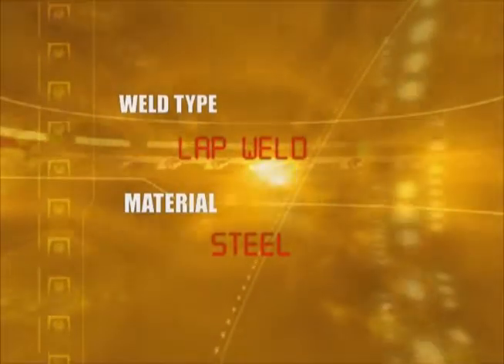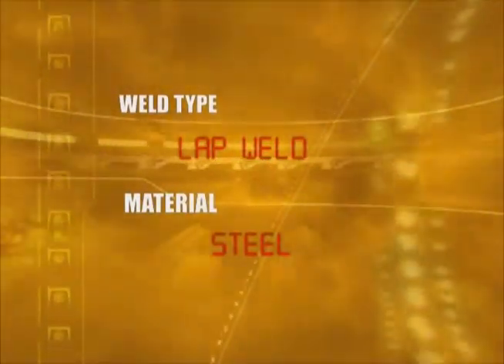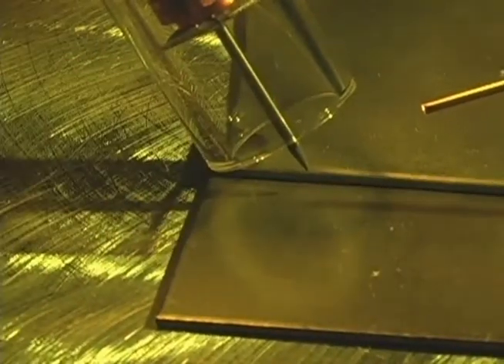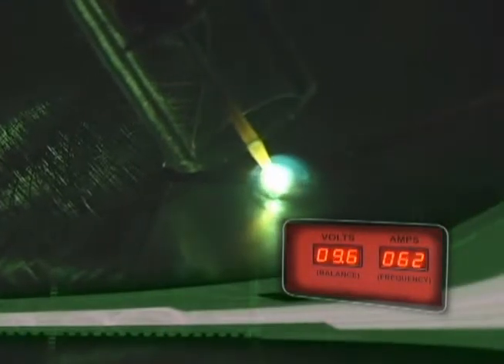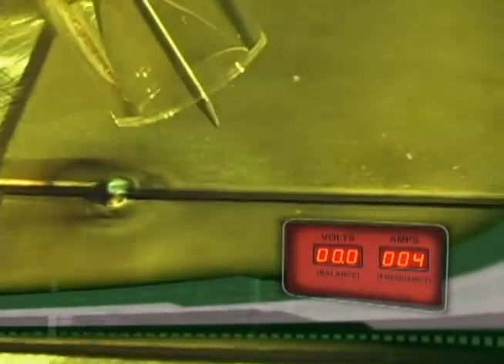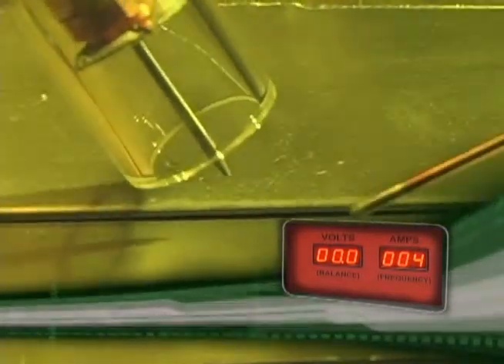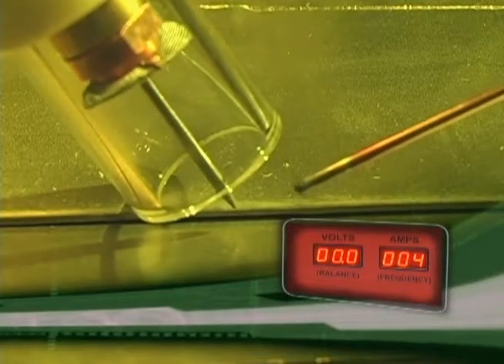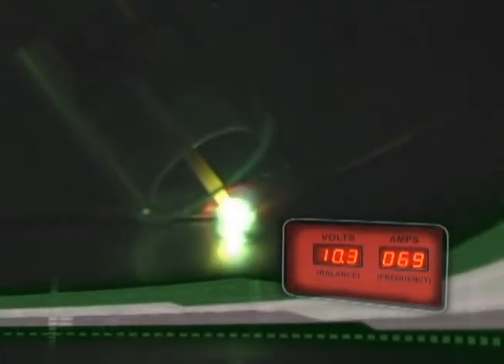Once you have become proficient in laying down a nice bead on a butt weld, the next weld to learn is the lap weld. A lap weld is where one panel is placed on top of the other panel. We will tack the panels together to prevent warpage. When you initiate the arc, keep the arc and the heat on the lower panel. The arc will always try to go to a sharp edge, so you may have to move the torch to force the arc to the lower panel.